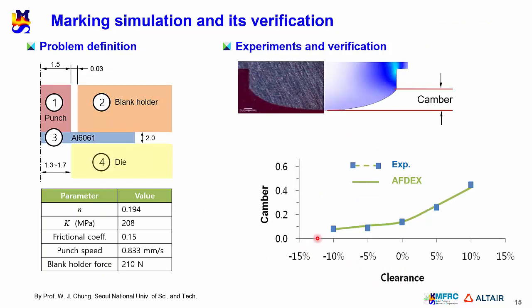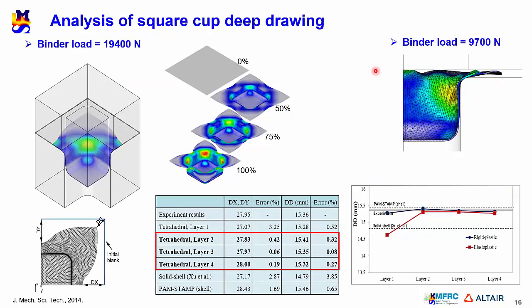Marking simulation was conducted to be compared with the experiment in terms of the maximum length of the extruded part defined as camber. We found that AFDEX followed the experimental point with higher accuracy. A square cup deep drawing process was simulated to investigate the effects of the number of layers on the predictions. We found that 2 is good for the minimum number of layers in this case, as can be seen in this comparison. With a normally small binder force, we obtain irregularly shaped material, as can be seen here.